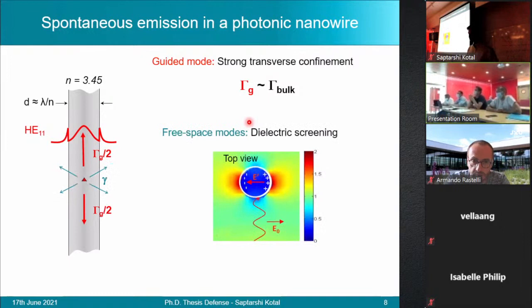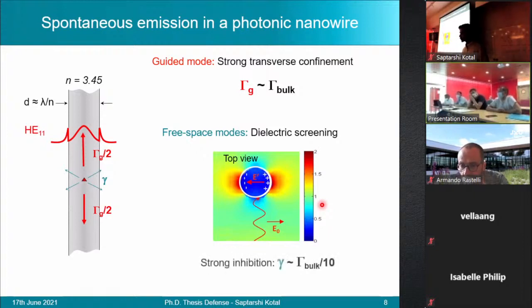Additionally, a dielectric screening effect significantly reduces the coupling of the emitter to free space modes. This happens due to the suppression of the zero-point fluctuation of these modes within the material. In other words, the free space modes have no means of getting into the wire itself. Therefore, the emitter has no possibility of coupling to them. And in the process, we can achieve almost an order of magnitude in inhibition of these free space modes.